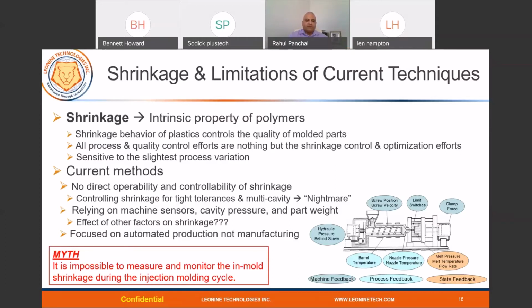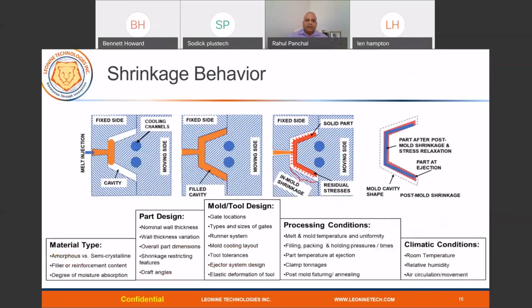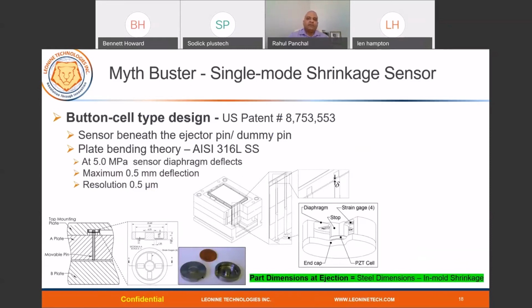There is a myth that it is impossible to measure and monitor the in-mold shrinkage during the injection molding cycle. I'm not going to go into this detail, but this shows how it behaves, and we covered this information before. So this is the myth buster that I developed several years ago. It's an in-mold shrinkage sensor, which is patented. It's designed based on the button cell type of design, fabricated from 316L stainless steel, which is sensor grade stainless steel material.